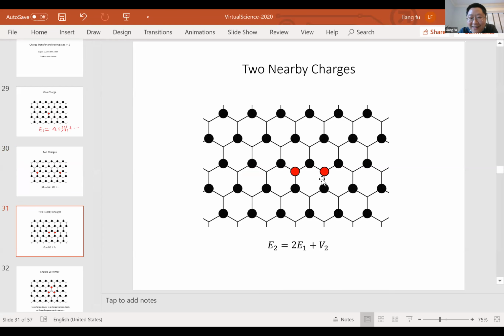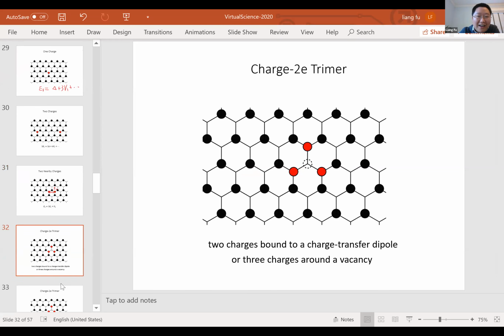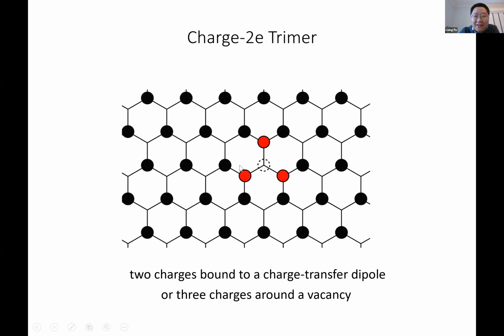Bringing these 2 charges together costs more energy, because now there's an extended interaction, a second neighbor interaction between them, which I call V2. So that's not favorable at all. But let's now look at this alternative scenario. When we bring 2 charges close to each other, at the same time, we transfer a background anion charge to the neighboring cation site. So we form an object which consists of 3 charges around a vacancy, or you can think of it as 2 added charges bound to a charge transfer dipole. So I have transferred a charge in the background to a cation site.